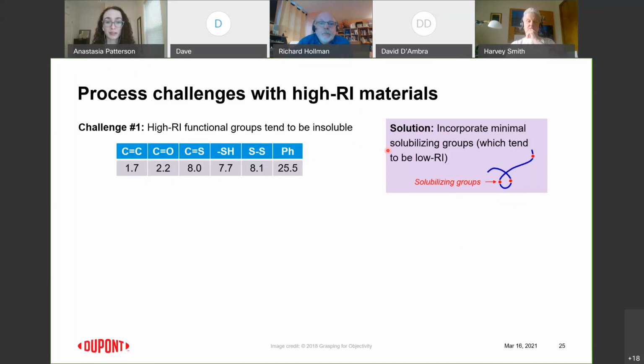So what we can do is dose in just a little bit of solubilizing groups, which tend to be low refractive index, but we can get away with incorporating a very low amount, just enough to solubilize the material. So that was one of the first lessons we learned in this project.